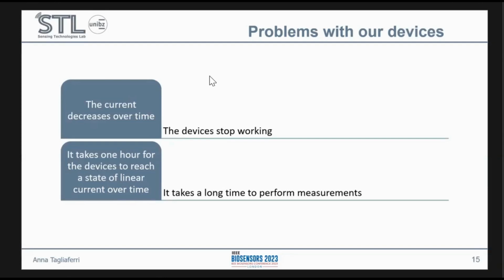For the third example that I have shown you, it takes 1 hour for the device to stabilize and to reach a state where the current is linear over time. After this, we have to leave the devices to equilibrate for another 40 minutes, which means that it takes a very long time to perform the measurements. And it is not feasible nor sustainable for our application of continuous sweat measurements on athletes. We cannot leave them cycling or running for 2 hours and a half before starting the measurements. And so it's from these premises that my work began.